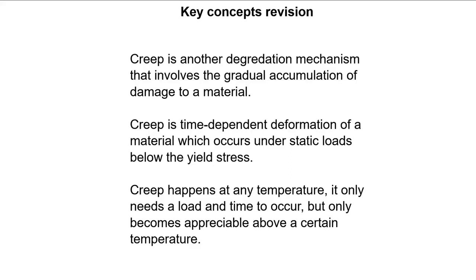In this way, dislocations can free themselves from a pinning obstacle and move under the influence of the applied stress. Dislocation climb can only occur if there are enough vacancies in the lattice. During creep, dislocations go through a continuous process of climbing, gliding, becoming pinned again, and then climbing free. The dislocation climb process relies on substitutional diffusion in order to free dislocations from obstacles. The higher number of vacancies occurring at grain boundaries explains why fine-grained materials are more susceptible to creep.